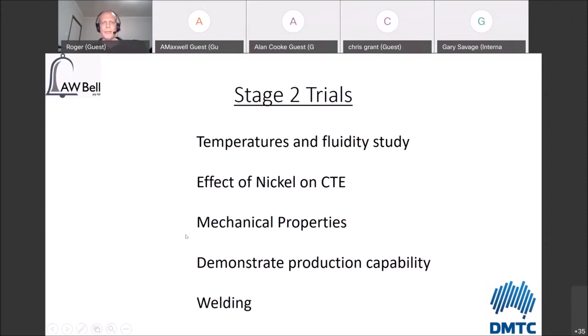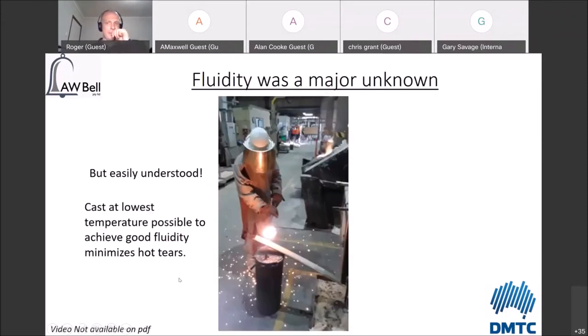Basically, these top 4 are the ones that I'll continue talking about right away. Fluidity was a major unknown. We knew that we had to have high fluidity to get to these very thin wall thicknesses, but we had this issue with hot tearing, so we had to go as cold as possible to achieve good fluidity.